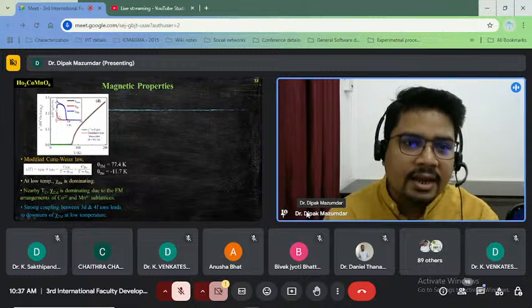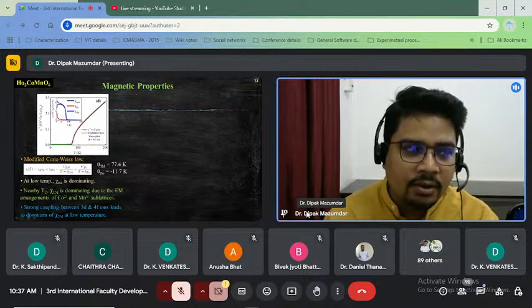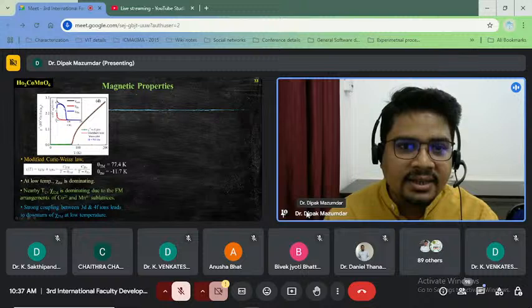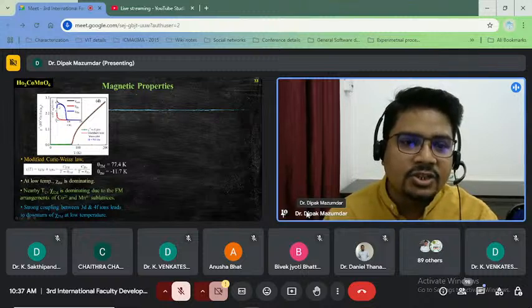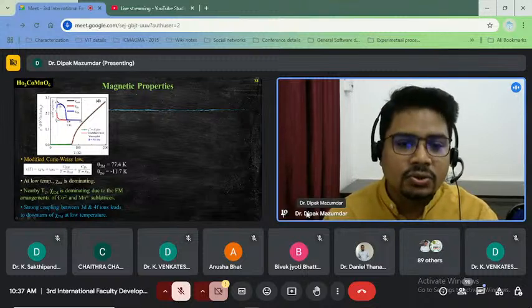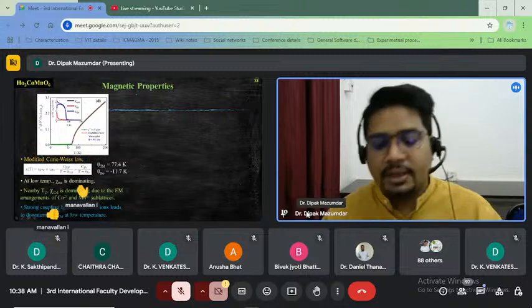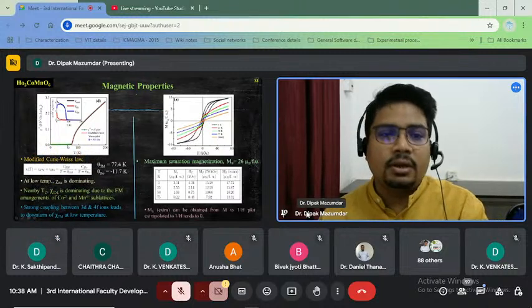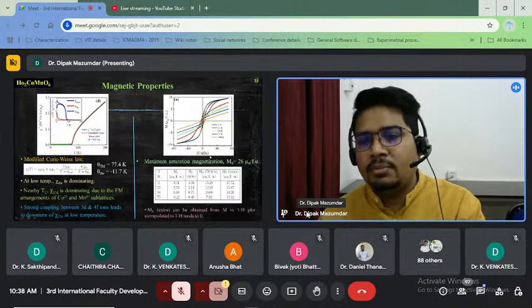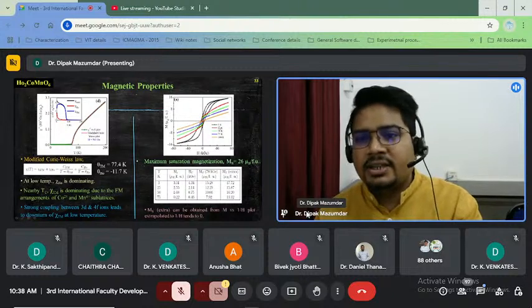So you can see at low temperature the holmium ions are dominating, but near the TC region the transition metal ions are dominating. So we can observe a strong coupling between the 3d-4f exchange interaction in the total magnetization of the system. Next, we will discuss the isothermal magnetization data recorded at several temperatures.